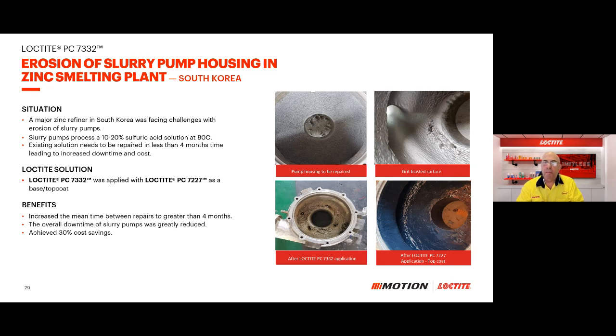You can apply it. There are methods to wetting out the surface first, and one of these is to mix up some of the product, rub it over the surface to create a sticky primer coating, and then apply the wearing compound. This ensures that you get down into all those little nooks and crannies, and you can see in that grit blasted surface on the right hand side picture there how the particles have worn little grooves in the surface. Quite often, because wearing compounds are quite thick and pasty by nature, you would want to apply a primer coating first, and then apply the wearing compound over the top to give you the best possible adhesion, because you've now got epoxy getting right down in all those little tiny grooves and things, and you get the best possible adhesion.